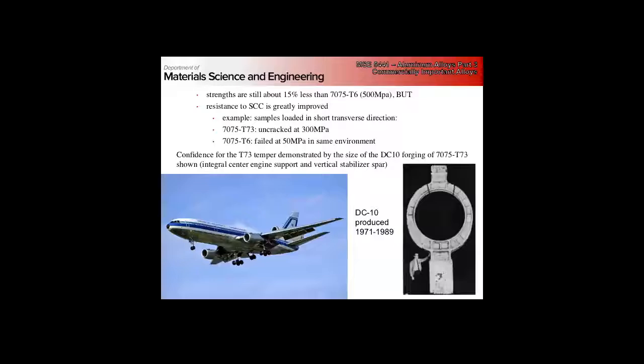And this was used to great effect in very large forgings for the DC10, for alloy 7075, this T73 temper. The DC10 was out of service by the time most of you were born, but it was a triple engine plane with the third engine being in the tail. This is the forging - this is the engine mount, the spar for the tail section, and this was a single forging made out of this 7075 with this T73 temper. It was basically the only way we could make these at this time.